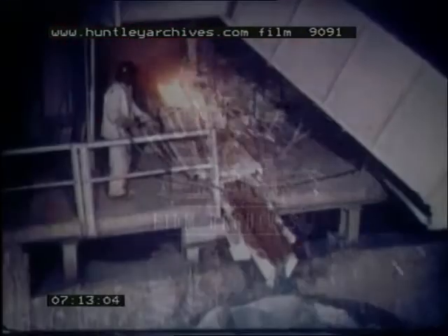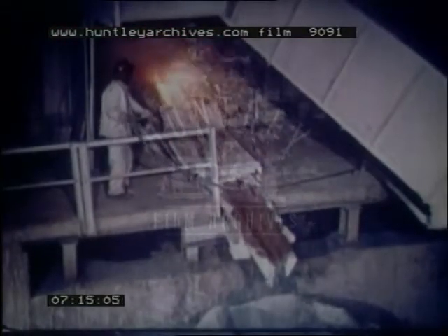The copper matte runs through a channel to a furnace, which will keep it at the right temperature while awaiting conversion. As for the slag, this is granulated by cold water before being dumped on the slag heap. The holding furnace is opened by means of a blowtorch. The matte is cast into steel ladles of 4 cubic meters capacity, or 15 to 20 tons.